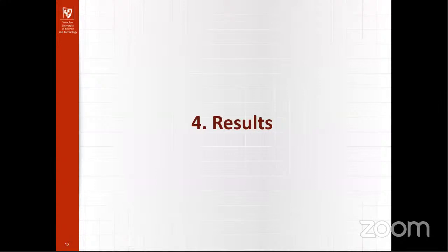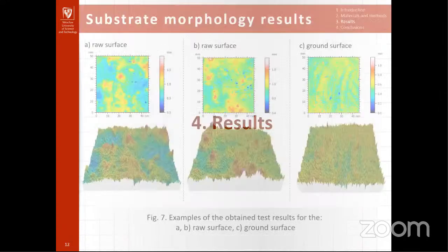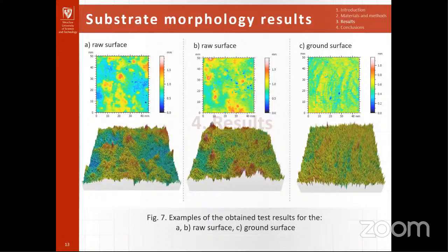Going to the test results. Figure 7 shows a comparison of the exemplary results of the surface morphology examination of both types of substrate surface using a 3D laser scanner. The raw surface was more varied between the measurement points. For the raw surface, there were greater differences between the highest and lowest points compared to the ground surface. For the ground surface, the examined areas look almost the same as in Figure 7c.